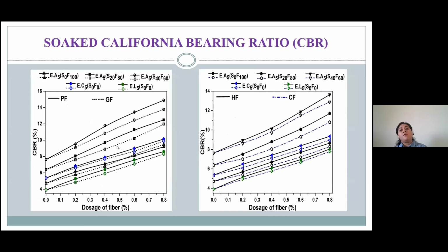We have also carried out soaked California Bearing Ratio tests, and as we know, CBR indirectly gives a clue for the long-term efficiency and working condition of the material. During the period of soaking, we soaked it for 4 days as is done in the soaked CBR test.